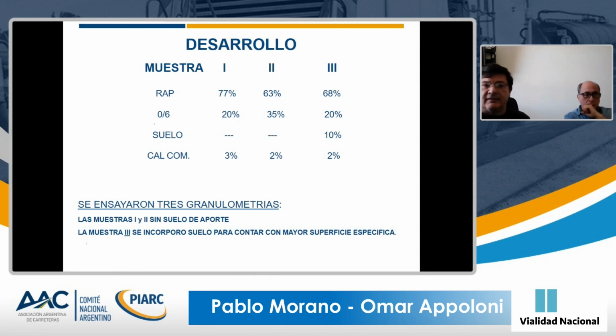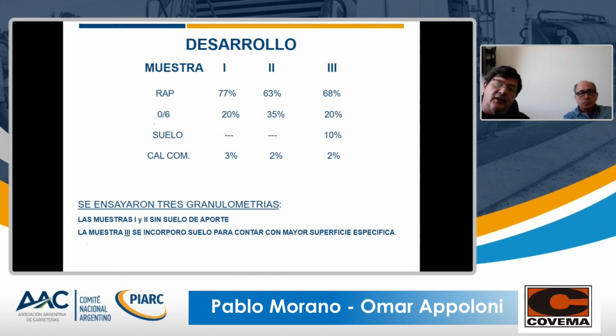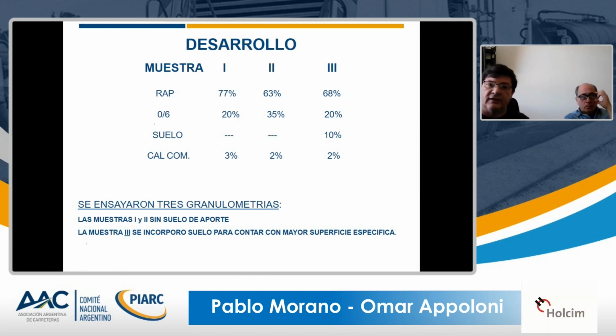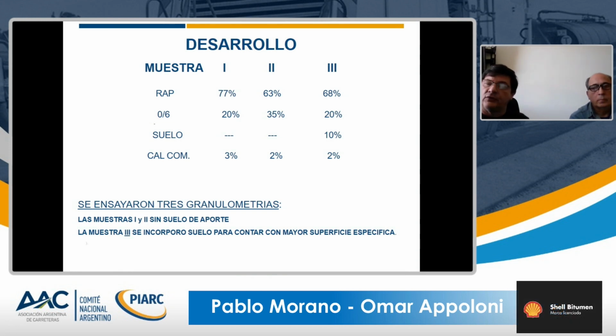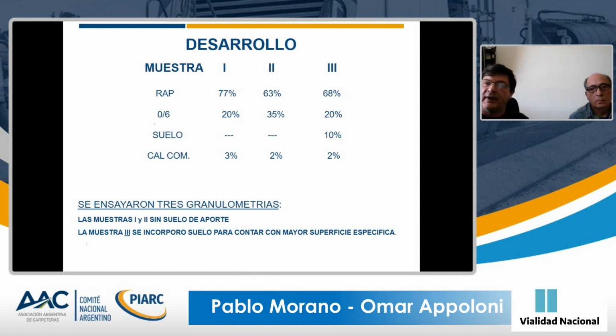We started developing types of mixes, and we had 3 curves so that we could define which one we were going to use. In the first one, as you can see, we had 77% of RAP. It was corrected with 20% of sand and 3% of commercial lime. In the second one, we had 63% of RAP, crushing sands were 35%, and the percentage of commercial lime was only 2% to act as a filler. And in curve number 3, it was intermediate. It was 68% of RAP, the crushing sand 0.6 was 20%, 10% was soil, and 2% was commercial lime.